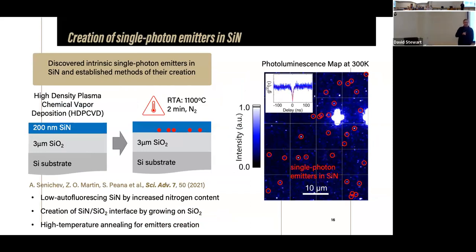The other one is, it turns out that you have to do this rapid thermal annealing to create these single photon sources. And from this stage, basically, I'm starting to speculate. We don't know yet for sure the nature of these emitters, but it looks quite plausible, at least our idea about this emitter. So when you do this rapid thermal annealing, our silicon nitride is sitting on a silica substrate, and it's important. If you don't have a silica substrate, you don't have emitters. Actually, we believe that the emission comes from the interface, not from silicon nitride itself, which is actually good. It means that they all have one and the same z coordinate. They all sit in the same xy plane.